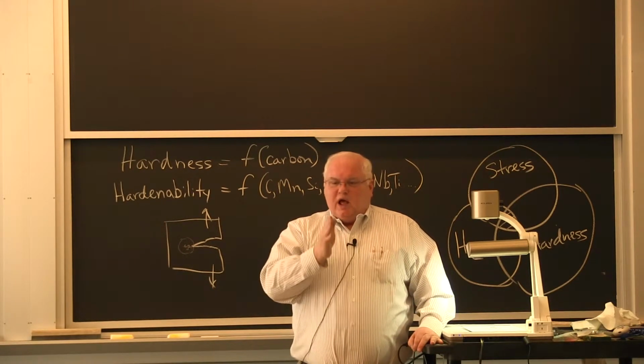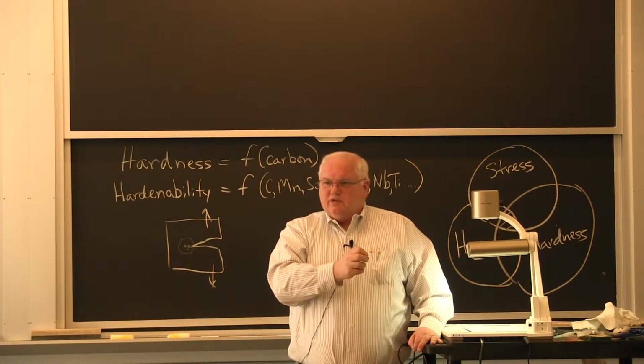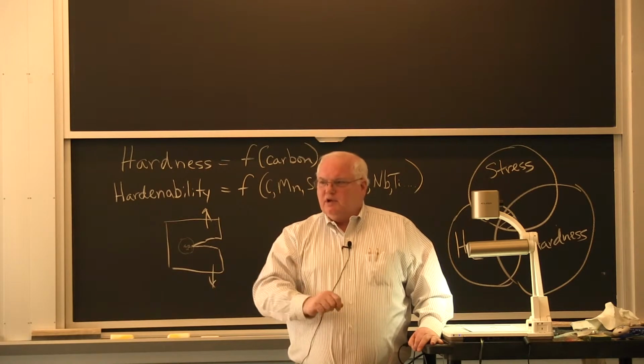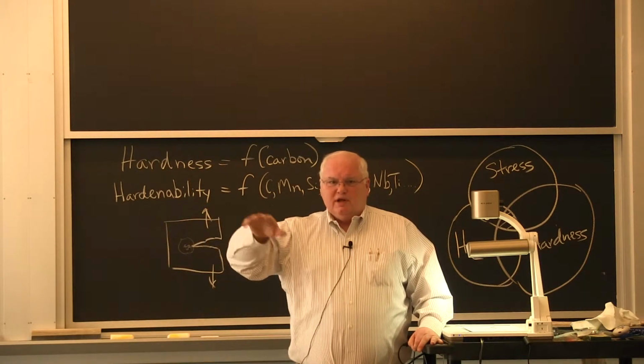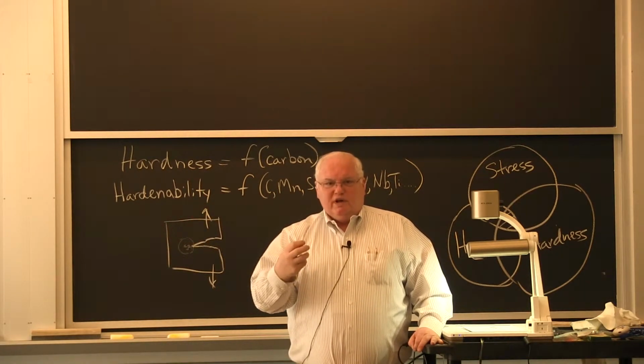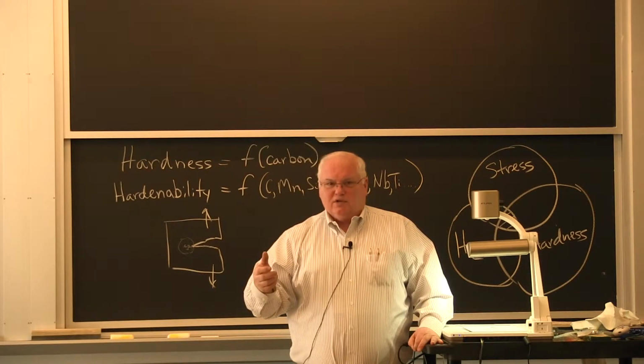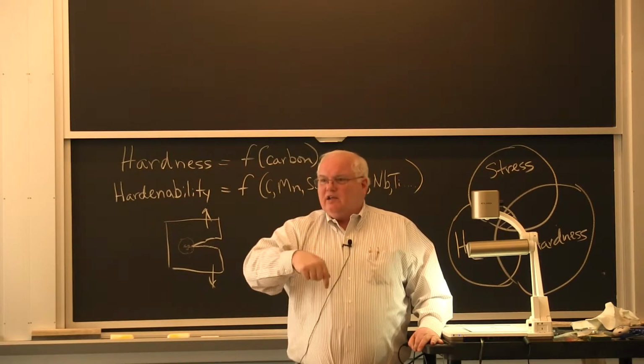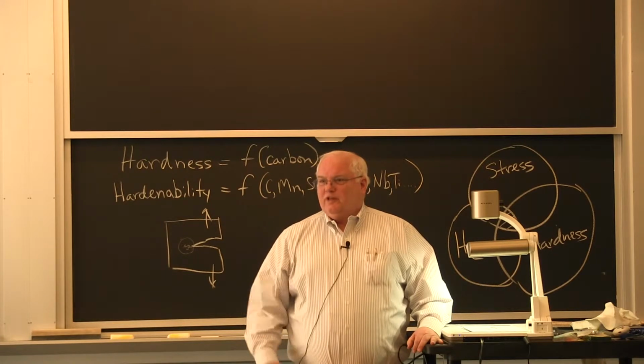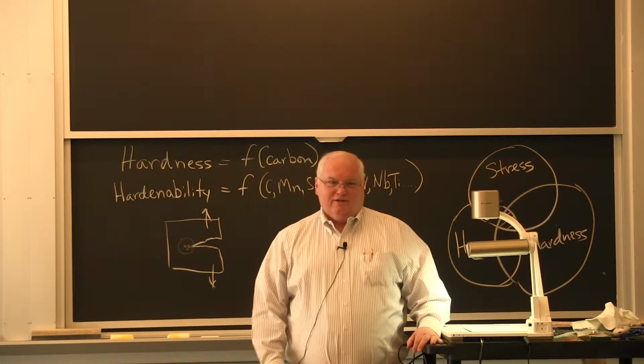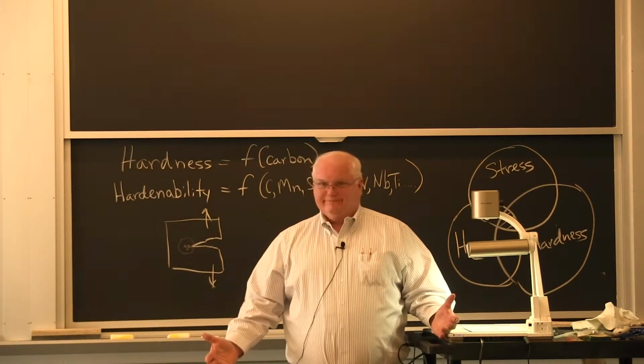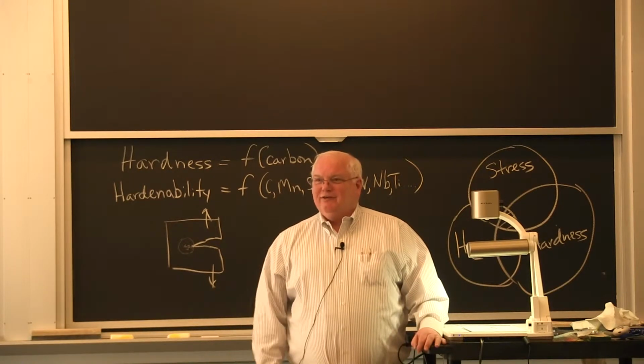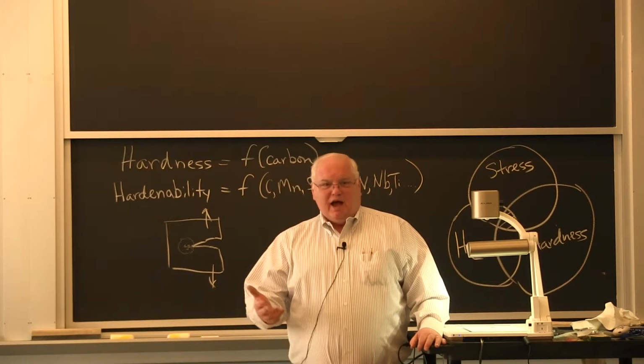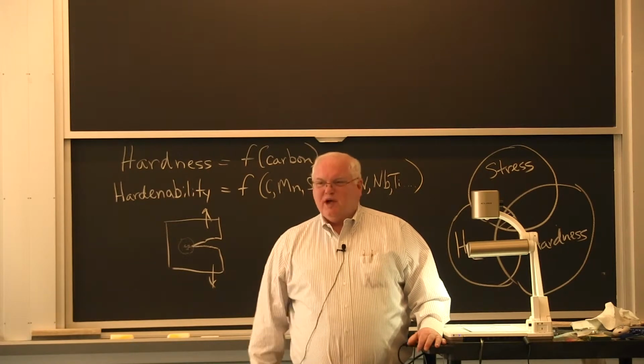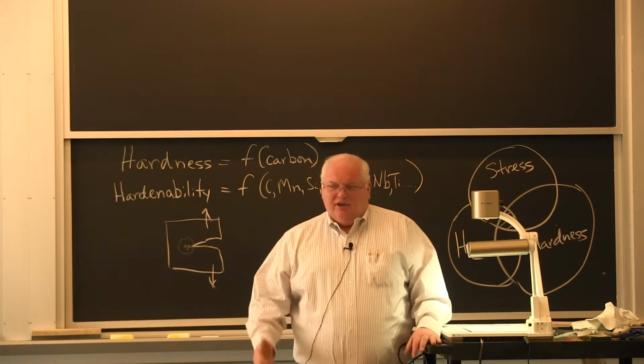As soon as they would get it out, they would have one sample, one destructive sample from the lot. They would cut off an end, send it off to the MET lab, and 2 or 3 days later they would get back the reading of how thick the nitride layer was. And that's when they started counting the 1 to 4 hours, when they got the results back 2 or 3 days later. Oh, how clever. Okay? Probably makes sense to some accountant, but I'm seeing a few smiles. To an engineer, it doesn't make a whole lot of sense.